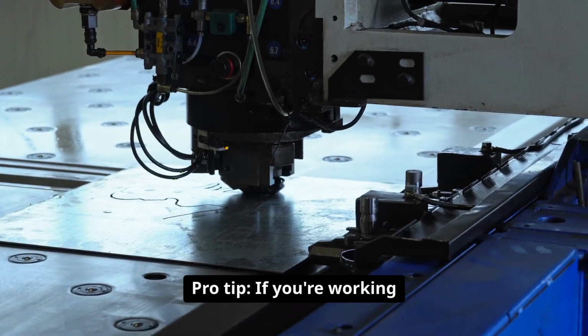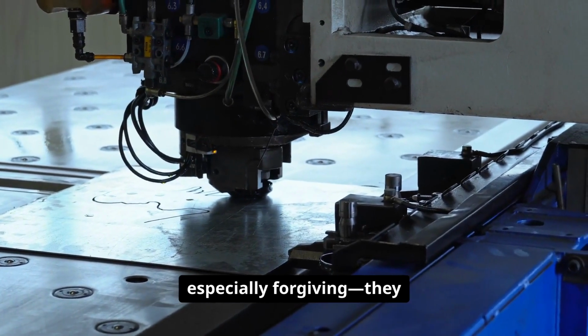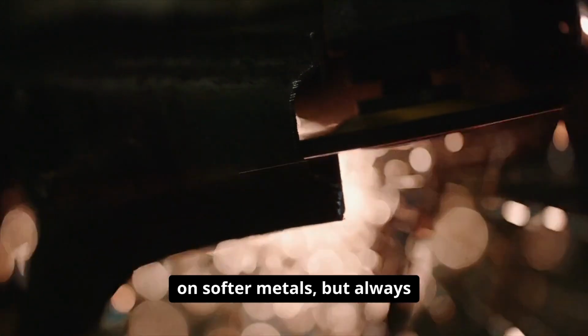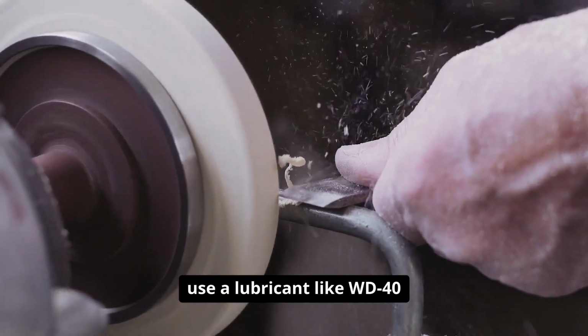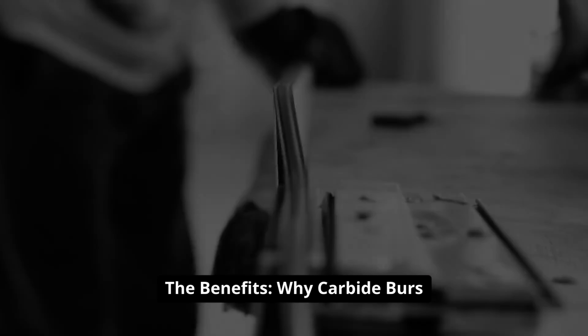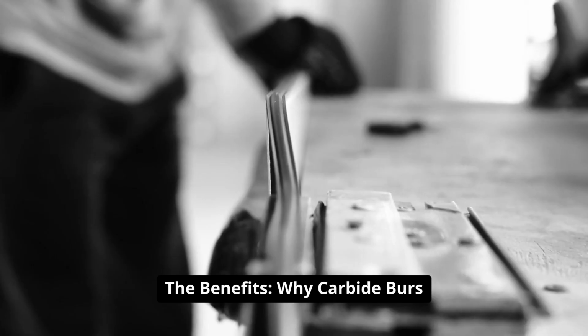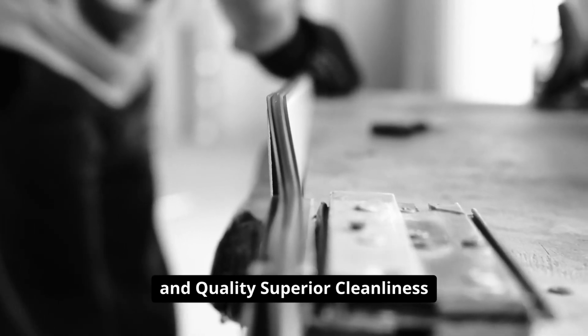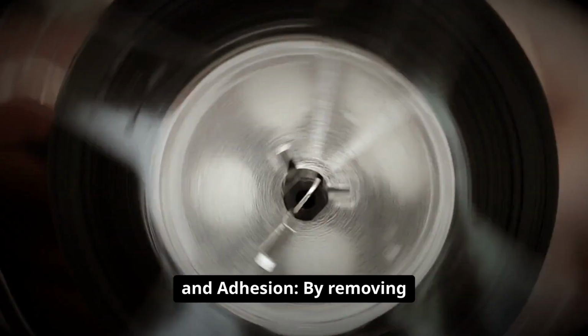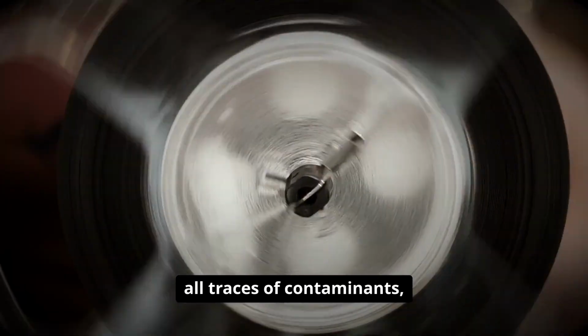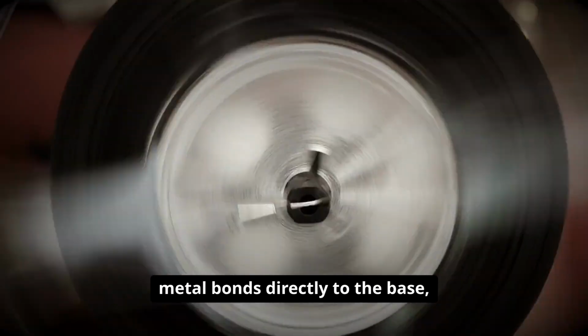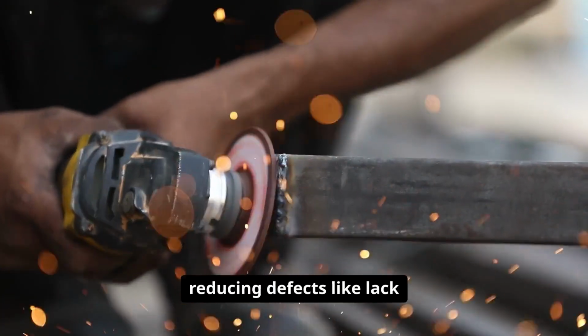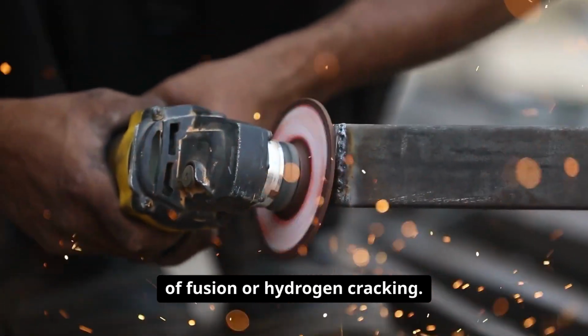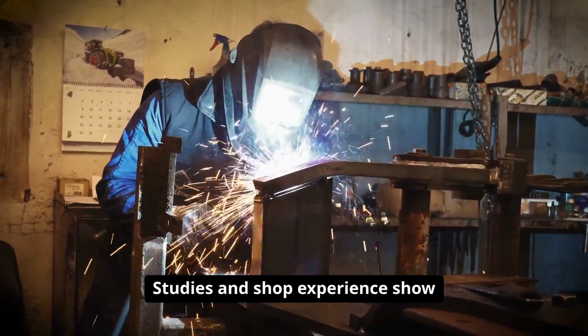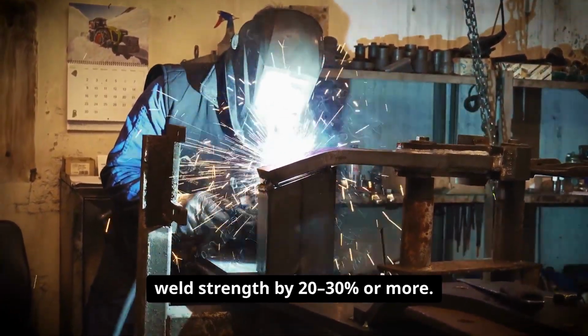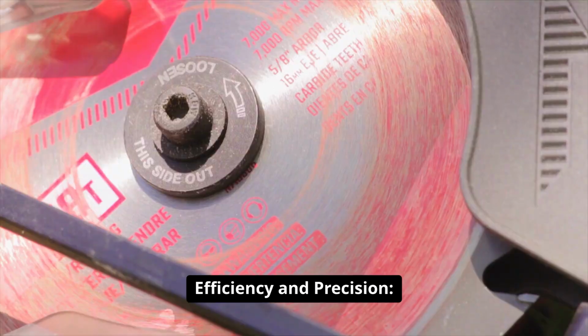Pro tip: if you're working on aluminum, carbide burrs are especially forgiving. They won't load up as easily as on softer metals, but always use a lubricant like WD-40 if needed to keep things cool. The benefits: why carbide burrs lead to better weld adhesion and quality. Superior cleanliness and adhesion. By removing all traces of contaminants, carbide burrs ensure the weld metal bonds directly to the base, reducing defects like lack of fusion or hydrogen cracking. Studies and shop experience show prepped surfaces can improve weld strength by 20 to 30% or more.